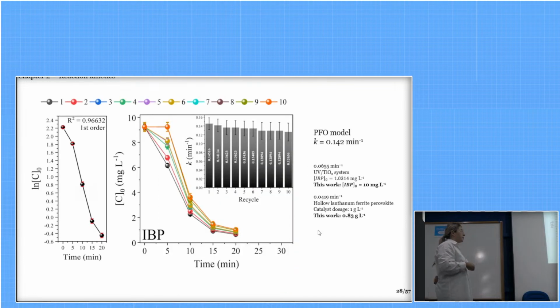We investigated the reaction kinetics for all the pollutants we studied, and the kinetic for ibuprofen fitted best to the pseudo first order model, and the kinetic rate observed was superior to those reported for conventional systems such as ultraviolet and titanium dioxide, and using hollow lanthanum ferrite perovskite, where we observed that our catalyst was able to degrade over 10 times more pollutant faster, and with 1/4 less catalyst needed than the ones reported in the literature.